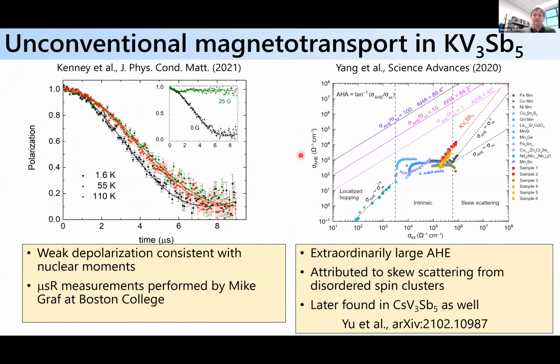So I guess some of the initial interest in this system is that Brendan grew single crystals of these materials, which were still somewhat potassium deficient. And so this is potassium vanadium 3 antimony 5. And then these crystals were studied by Maz Ali at Max Planck.